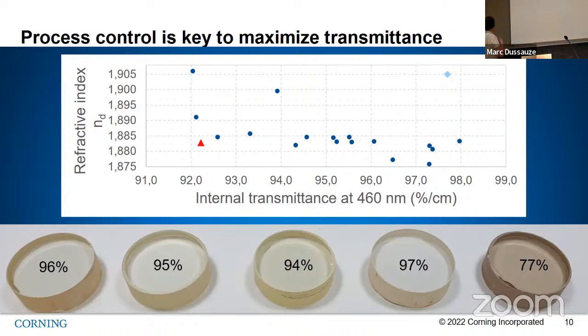And what I wanted to show you here are some pieces of glasses that we made in the lab. So they're always the same composition, and we are just changing the way we process it. So in the way we melt it, by changing some temperatures, time, some raw materials, you can see that for the same composition we can go from 77% of internal transmittance. When I say this number, it's always at 460 nanometer in the blue. And we can go up to 97% of internal transmittance.